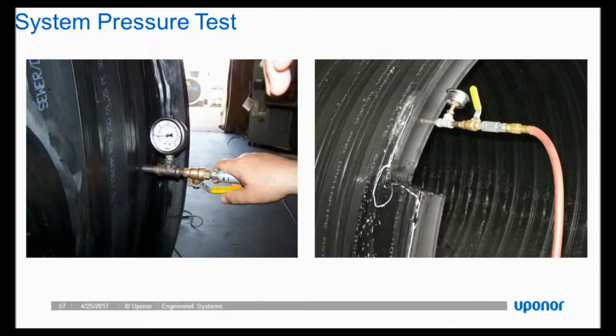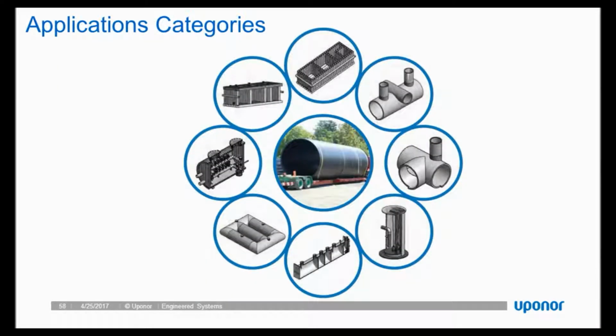Here you can see a snapshot of our pressure test at our facility, where we'll actually drill a hole in the annular space and pressurize it, turn the flow of pressure off, and then observe that it holds pressure, and then certify that. If it does not, we'll have to spray soapy solution, look for leakage in the area wherever that annular continuous profile is, and then regrind and reapply weld before it leaves the facility. It's just part of our quality control and assurance program.